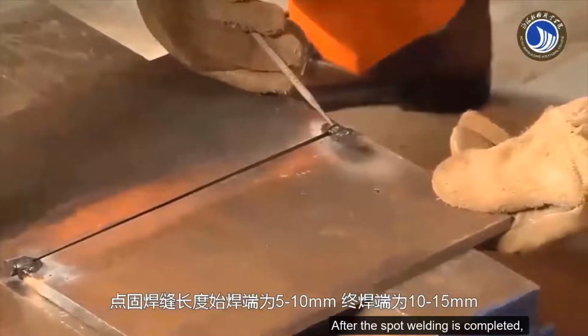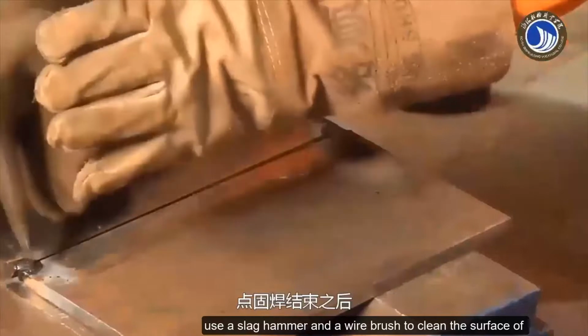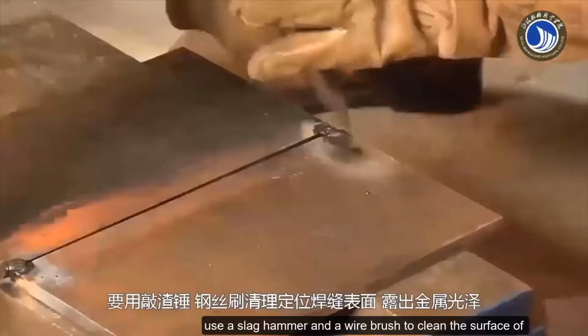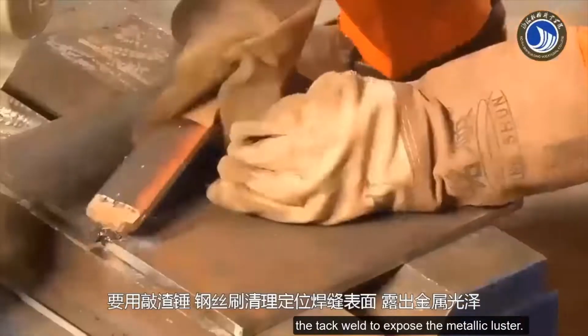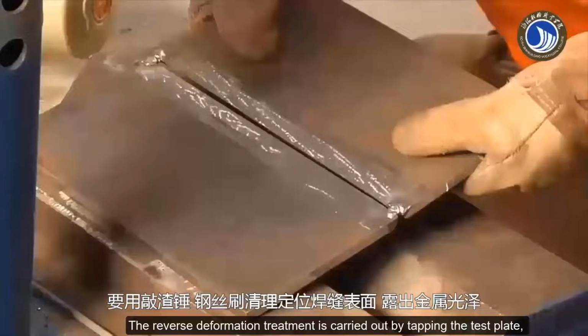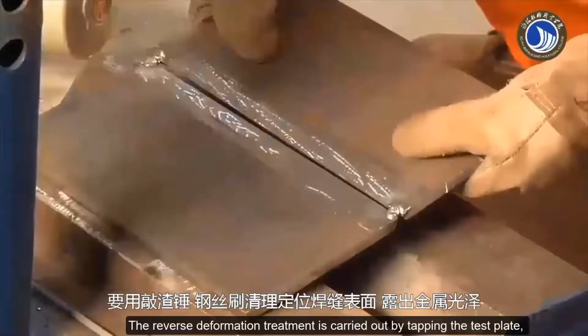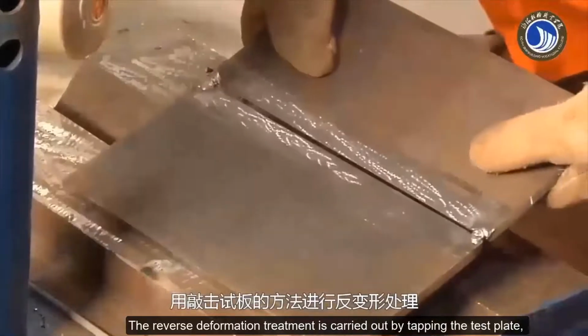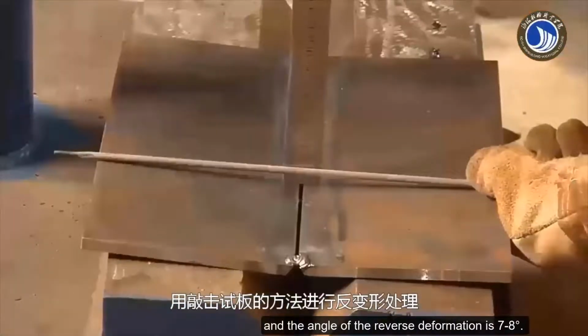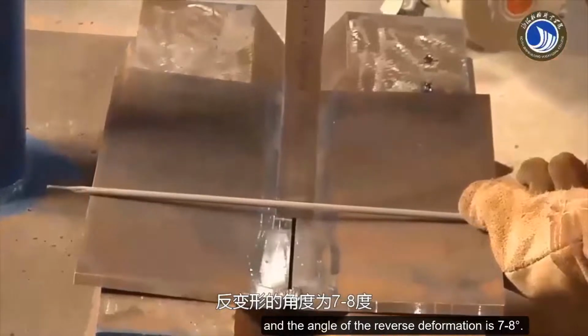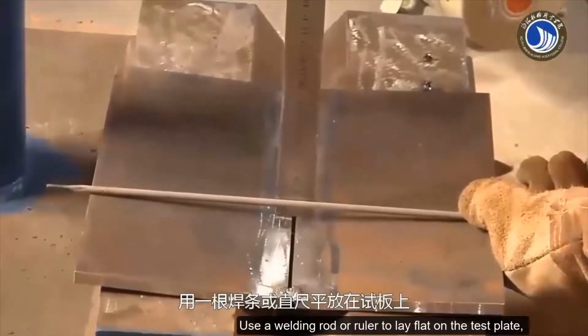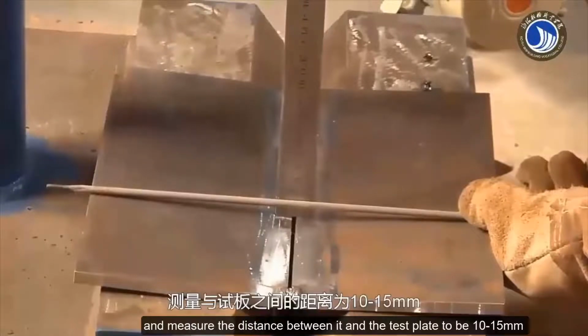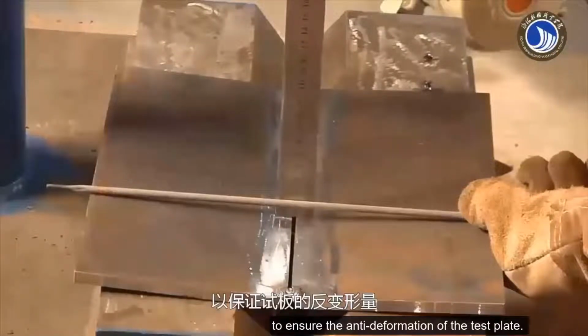After the spot welding is completed, use a slag hammer and a wire brush to clean the surface of the tack weld to expose the metallic luster. The reverse deformation treatment is carried out by tapping the test plate, and the angle of the reverse deformation is 7 to 8 degrees. Use a welding rod or ruler to lay flat on the test plate, and measure the distance between it and the test plate to be 10 to 15 mm to ensure the anti-deformation of the test plate.